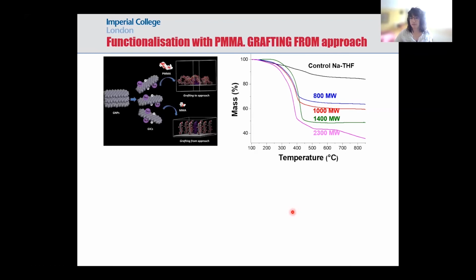Focusing on the grafting-from approach, where we add the monomer and then grow the polymer on the surface, we were able to customize the final polymer in terms of molecular weight. And we studied the different functionalities using TGA. From TGA, we are able to estimate the amount of polymer from the degradation between 300 and 600. From this degradation, we can calculate how much polymer we are attaching on the surface of graphene. As we increase the molecular weight of the polymer, we observe a higher mass loss.